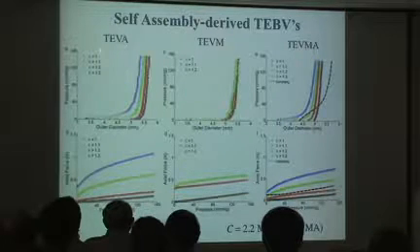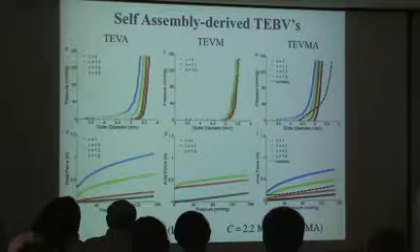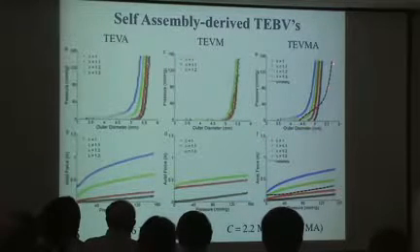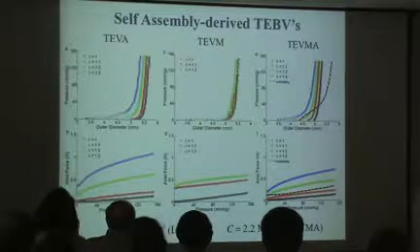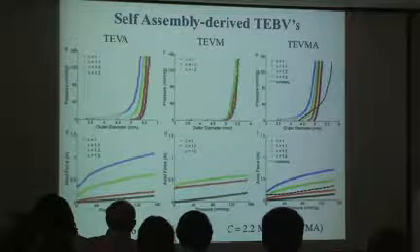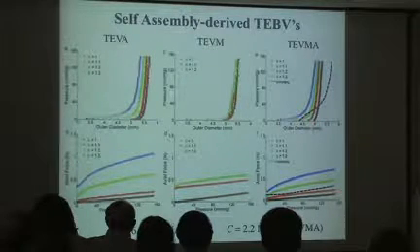These are representative curves of pressure versus diameter for the media, for the adventitia, and for the two-layer vessel. And this is the axial force again versus pressure, this set of curves. And this dotted line is a curve for our model coronary artery from Holzapfel's group. So we can see that these vessels are pretty close to a representative coronary artery, right? Here the diameter is a little bit off, but we can control the diameter by controlling the size of the mandrel that we wrap these sheets around.